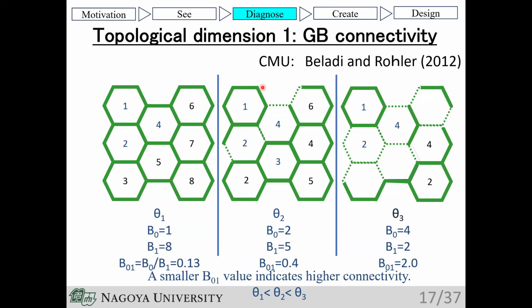Regarding grain boundary connectivities, the B0-B1 method proposed by Professor Beladi and Professor Rohrer at Carnegie Mellon University is a potent tool. While percolation theory is commonly used to study phenomena like stress corrosion cracking, the B0-B1 index offers a more rigorous correlation with fracture life. B0 represents the number of connected components, and B1 represents the number of loops, that means holes. A lower B0 over B1 ratio indicates a highly interconnected network of boundaries. This descriptor evaluates the edge-related connectivity and is thus classified as a one-dimensional topological feature.